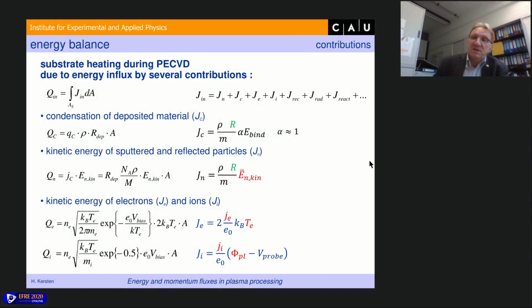These quantities. And as I mentioned, there is an integral energy influx from the plasma to the surface, but this energy influx consists of different contributions. And you can try to measure this integral energy influx, which I call here Q in. This is just the integral over the surface area of the substrate or over the probe of the energy flux density. And this energy flux density, which is an integral value, consists also, as I mentioned, of kinetic energy of electrons, of ions, of neutrals, of condensation energy, of recombination energy, of radiation energy, and so on.